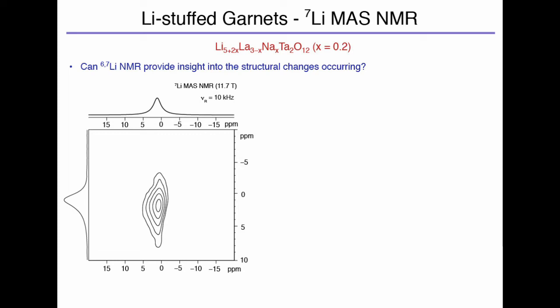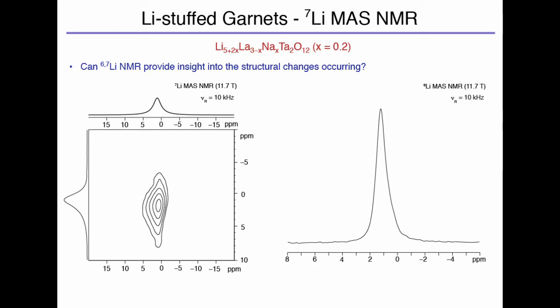So again, we can apply our two-dimensional techniques, and in this case, it's much, much harder to see that it's just a single ridge. It looks very broad, and it seems to be telling us that there's some sort of disorder or something unusual going on with the lithium. Because remember, we're supposed to have two distinct lithium sites, one octahedral and one tetrahedral, and we cannot differentiate between those two. So in some cases, when that happens, we can turn to lithium-6 NMR.